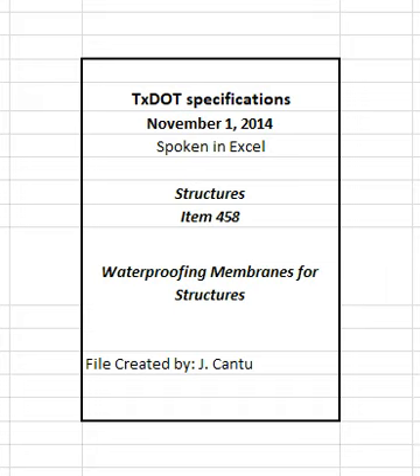3.3 Type 2. Place the asphalt primer at least 24 hours before the asphalt mopping. Ensure the primer is dry before the mopping. Work in the primer to give a uniform coating. Heat the asphalt for mopping in kettles equipped with armored thermometers, but do not heat above 350 degrees Fahrenheit. Stir the asphalt frequently while heating. Apply the mop coating at a rate of at least 4 gallons per 100 square feet of surface. Apply additional coatings, if imperfections appear, until corrected.